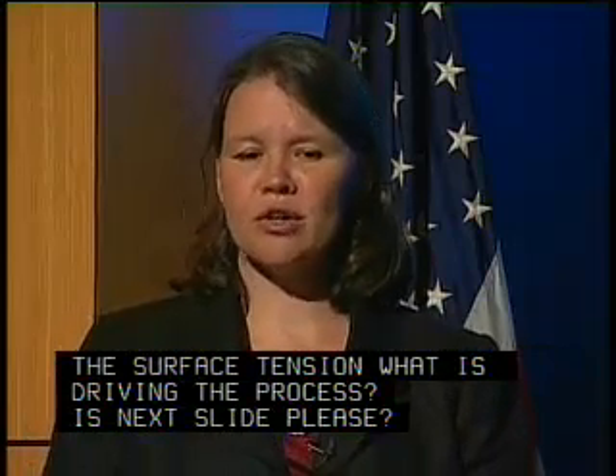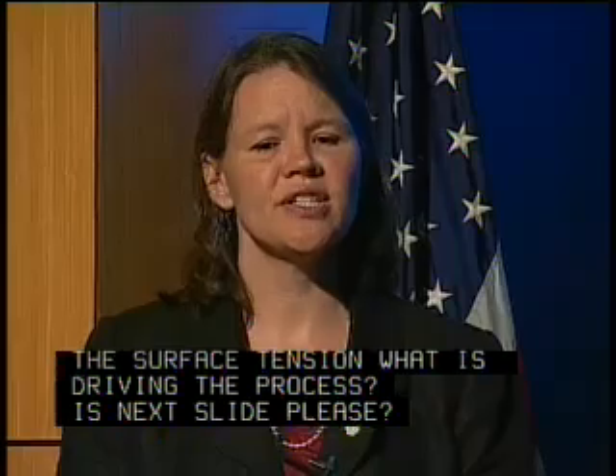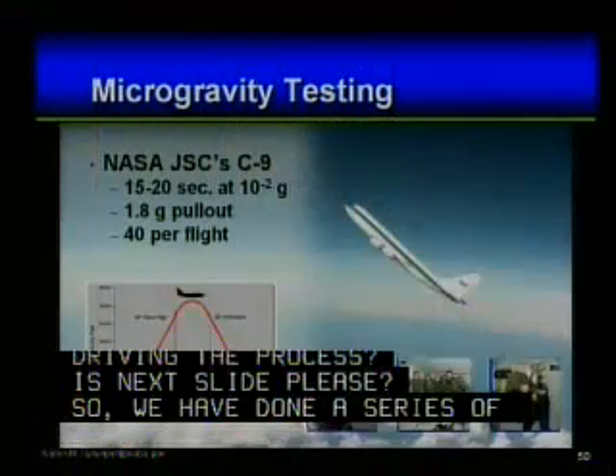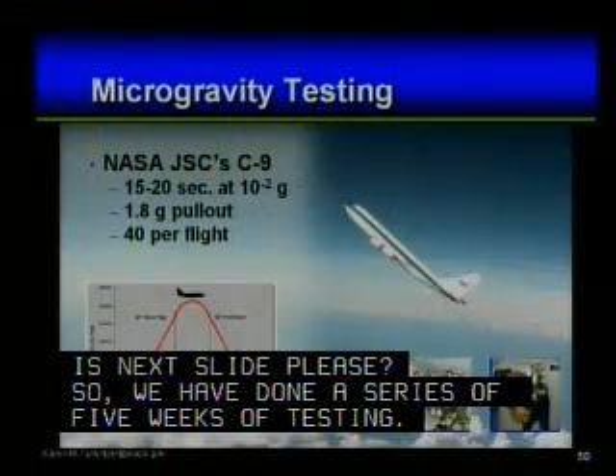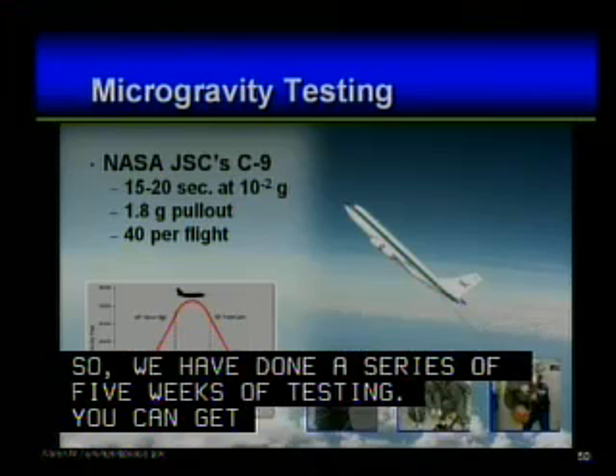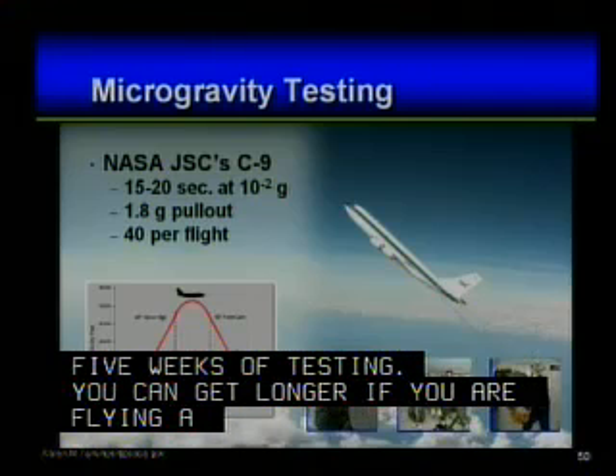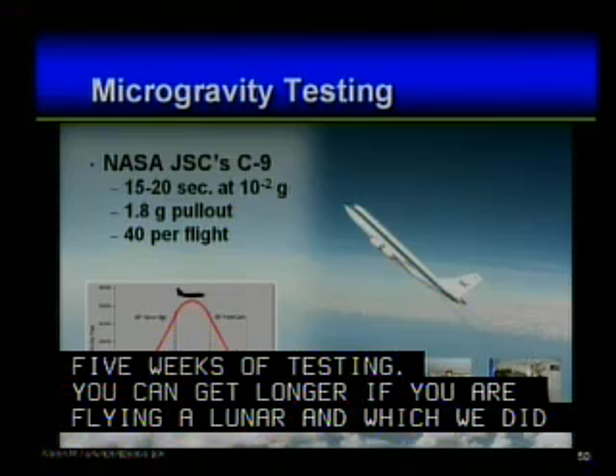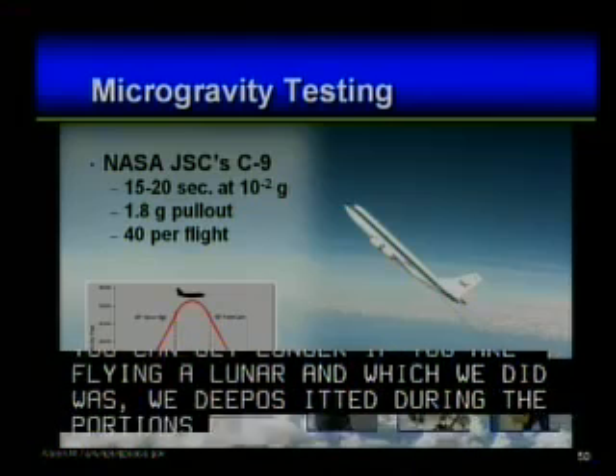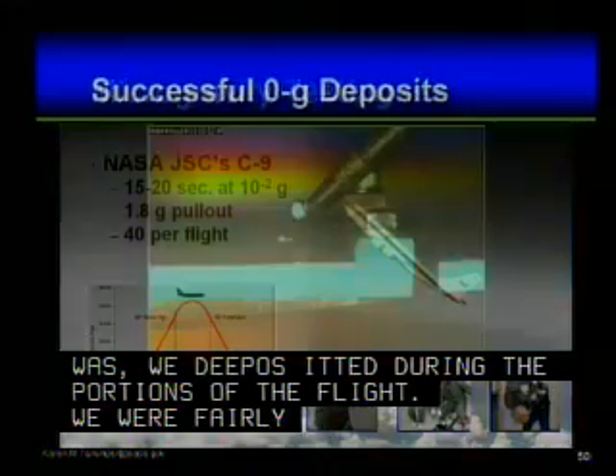Next slide, please. So we've done a series of 5 weeks of flight testing down at NASA JSC on their C9 reduced gravity flight. And for those of you that aren't familiar with that aircraft, they get on the order of 15 to 20 seconds of 0G. You can get a little bit longer if they're flying a lunar or a Martian parabola, followed by a 1.8 G pullout. And they do about 40 cycles per flight. And so what we did was we only deposited during the reduced gravity portions of the flight. Since everything solidifies as soon as we turn off the beam, we were fairly certain that we weren't changing anything during the pullouts. Next slide, please.